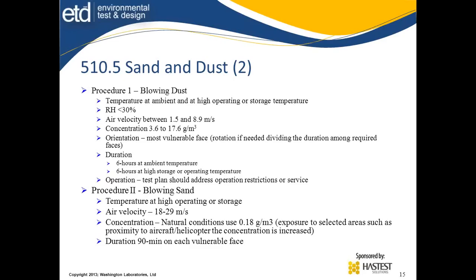The orientation says the most vulnerable face and rotation if needed, dividing the duration among the faces. So if you've got 6 faces that could be exposed here, you divide the total 6-hour temperature dust exposure, an hour for each one of the faces. And 6 hours again at the high storage or operating temperature. Again, at both these items, the duration is split among the faces. And the rotation applies to that, whether you're doing storage temperature or ambient.